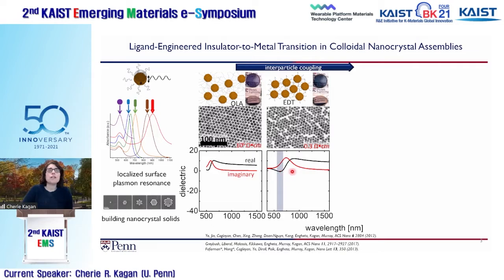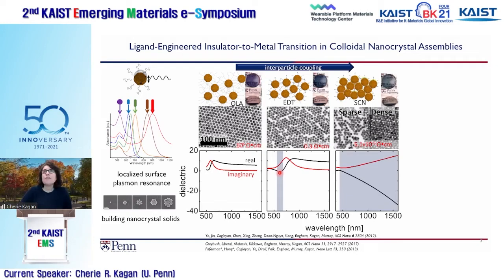And if you look here at its dielectric function, you just start to see, in a very narrow spectral range, that the real part of the dielectric function starts to dip negative. Something I'll also argue is consistent with this idea of traversing the insulator to metal transition. And finally, if we exchange with thiocyanate, of course, we lose more of that volume. Particles come closer together. Some of them begin to fuse. You can also see that in diffraction studies, where the characteristic gold lines narrow.